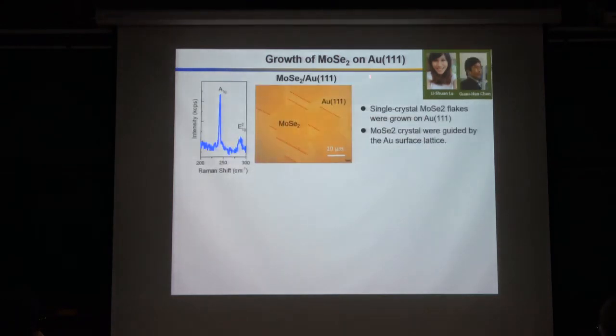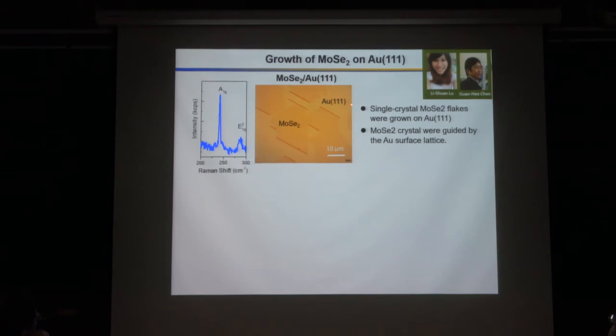Okay. We grow MoSe2 on Au(111). So you can see, I show you, the darker area is MoSe2, and this is the gold surface. So you can see the grain boundary. Actually, I highlight here, they are parallel. So they are guided by the Au(111) surface. So when they merge together, they can form large area, single crystal MoSe2.